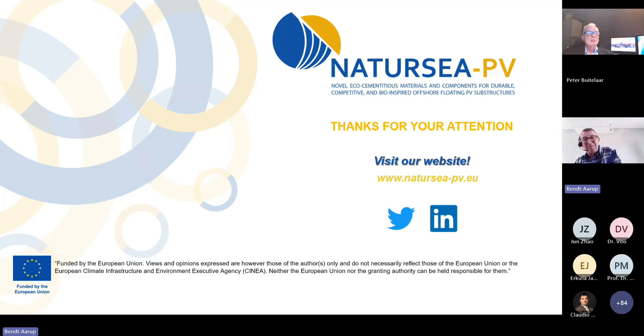We've looked at a lot of alternatives. Microsilica is very, very good. But there are some issues now also with the CSRD requirements in Europe, where we have to be more aware of where the materials are produced. And the white silica fume that we get is produced in either India or China. So it's a long distance to get it from. So we've looked at other types of material also. The very fine calcium carbonate, and typically we don't get quite as good performance as we do with the microsilica, so we're very slow to change.